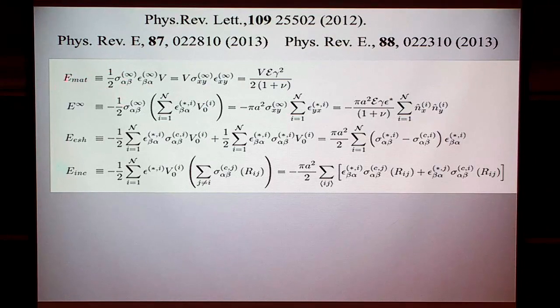So here there is a contribution from the material that is strained with the strain epsilon and has a stress sigma. So this is the contribution that you get from the material itself, whether there are Eshelbys or not. Then you have the contribution due to the strain in the material and the strain in the Eshelby. So this is the eigenstrain that I mentioned for each one of them, and you have to sum up from i to n if you have n such guys.